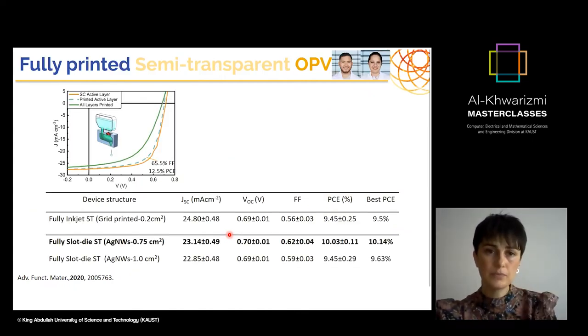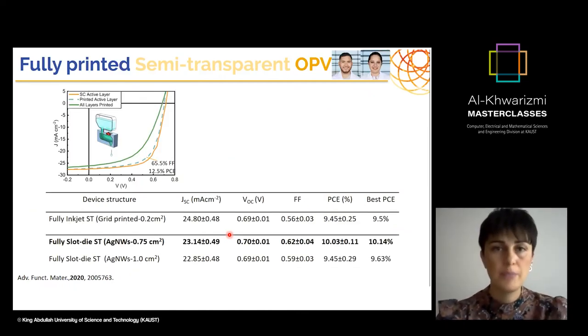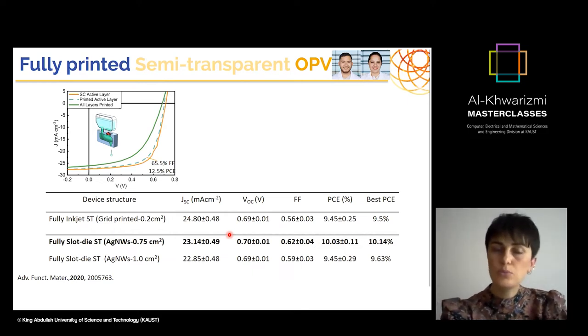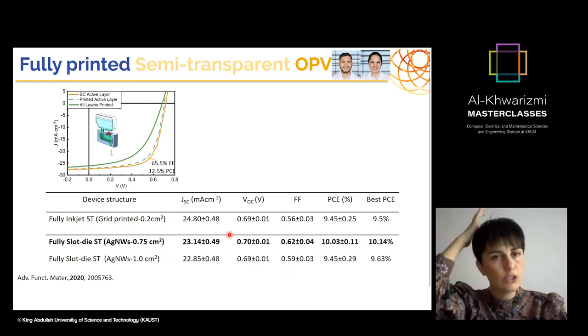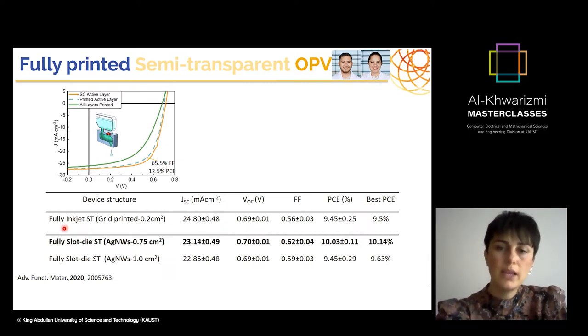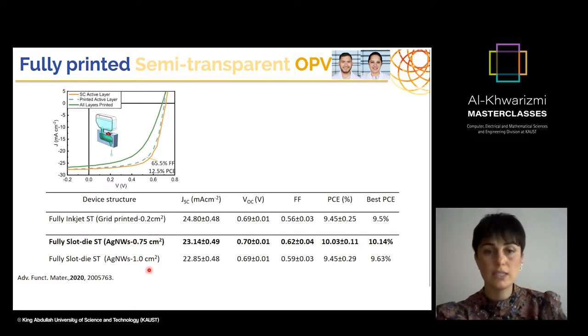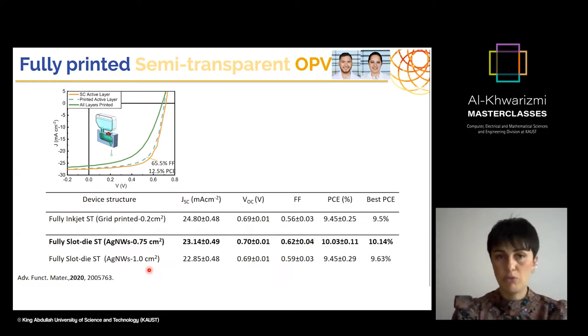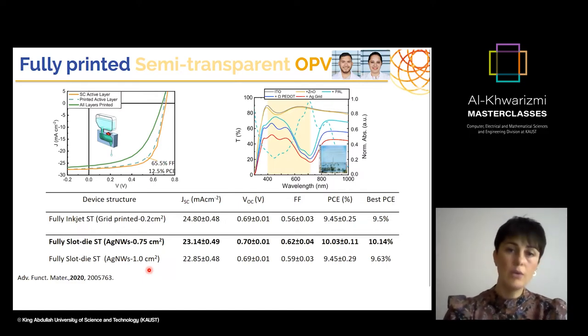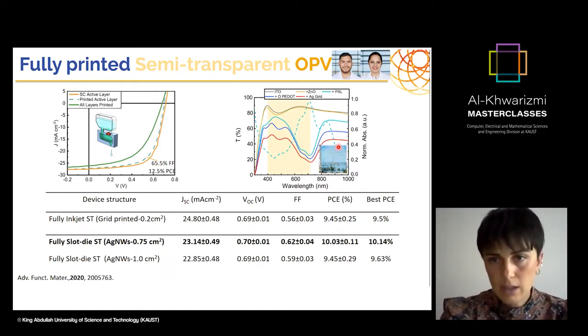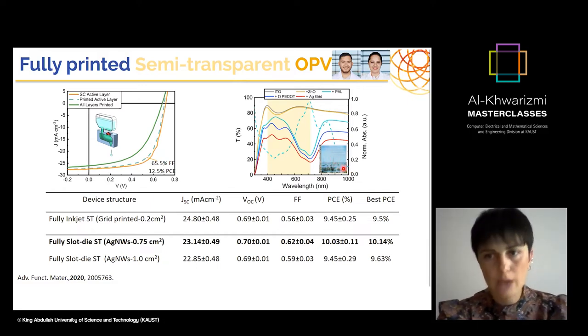Having ticked all the boxes for the efficient hole transport layer, we then moved to print and coat all the layers, as I showed in the device architecture. And we managed to reach 10% power conversion efficiency with 0.75 and even 1 square centimeter devices. As I said, this is a really nice breakthrough with this type of performance. But what is more striking here, I would like to have your attention, was when we printed our layers, how the whole device looked, as you see. And you can see at the back the beacon of KAUST.